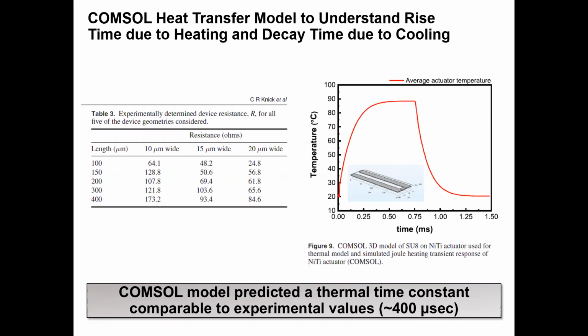In addition to the experiments, a COMSOL heat transfer model was also used to help understand the rise time due to heating and the decay time due to cooling. A physical model of the SU8 NiTi Joule-Heater was constructed and included standard material properties of the NiTi and SU8. When a 1-volt electrical bias was placed across the 2 electrodes, the Joule heating reached a steady state temperature in about 400 microseconds, which was very consistent with what was measured in the experiments. Similarly, the temperature upon removing the voltage source was mapped over time, and the steady state temperature was reached in a similar 400 microsecond time scale as well.